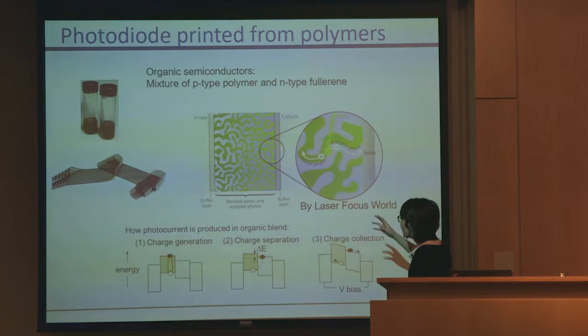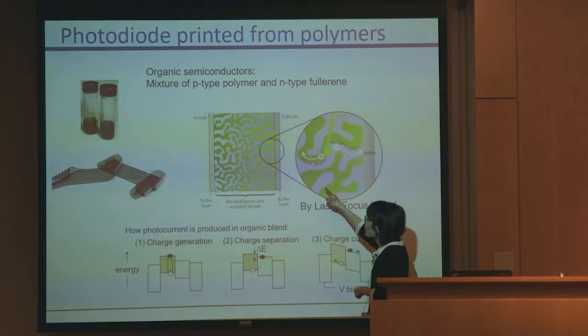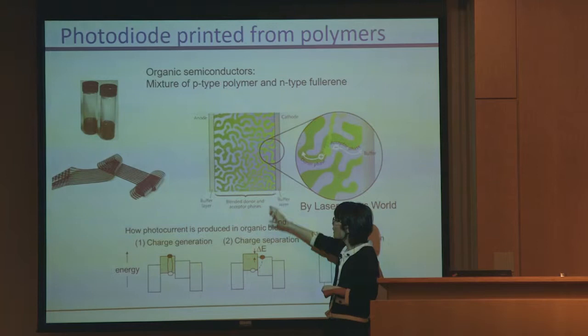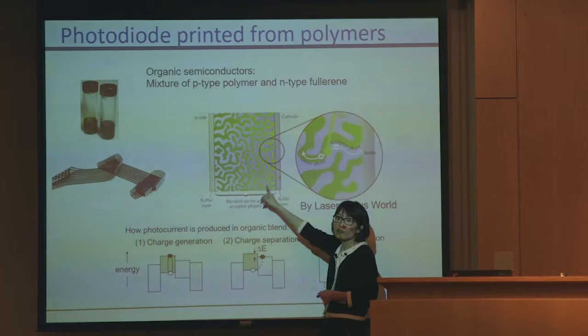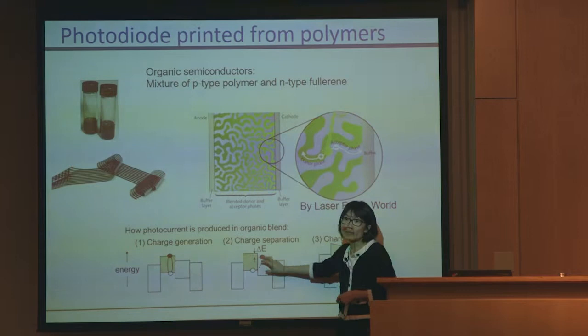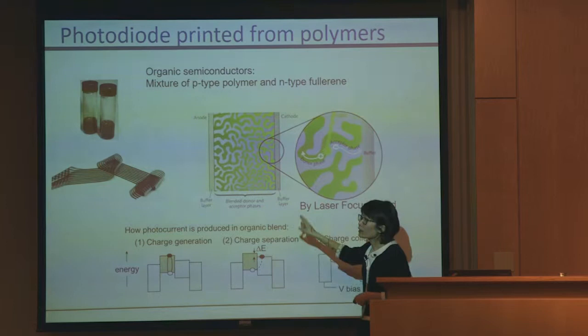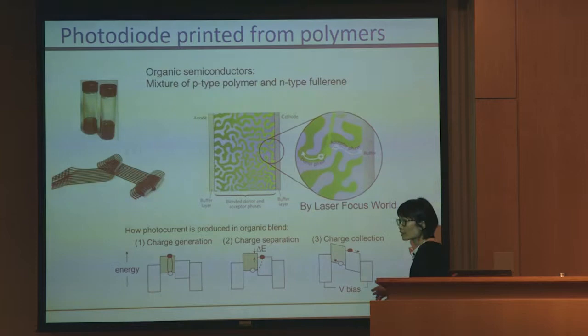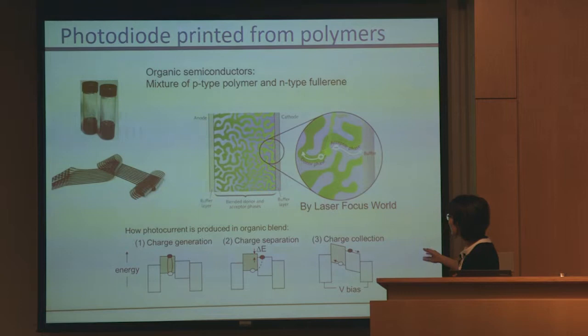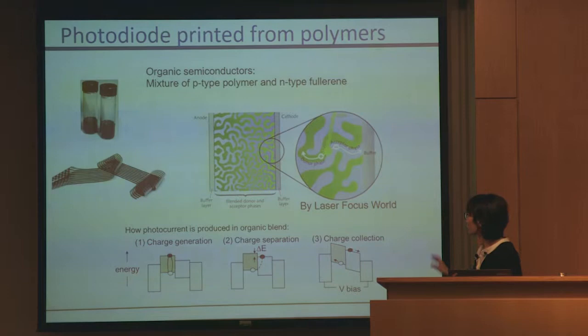And with this, we could actually have advantages. For example, when light shines at that photodiode layer, instead of being confined into the single interface at that P-N junction, now we have a lot of interfaces. And at the interface, because the two materials have different band alignment, it helps to separate the charge. And so with more interfaces, we have more band-facilitated charge separation mechanism to collect more photo-generated charge. And so that's how this photodiode works. In addition to being simple to process, it actually has pretty decent efficiency.